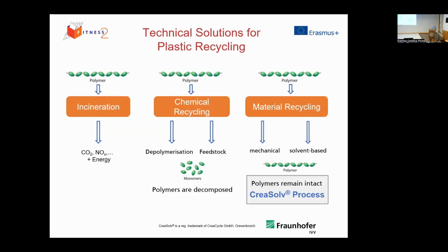But what exactly is solvent-based recycling? So at this slide you can see a comparison of the different most common recycling technologies. One of the most common one is still incineration, where you just burn your plastic waste and obtain a little bit of energy from it, but also greenhouse gases are emitted. And then there is chemical recycling, where you decompose your polymer to monomers or feedstock materials. But the most favored one should be material recycling, because in this recycling technology you don't need to polymerize the monomers again, but the polymer chain stays intact.